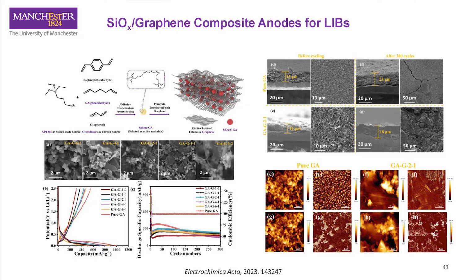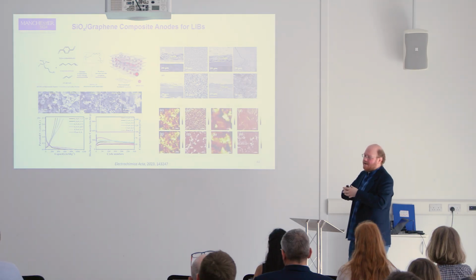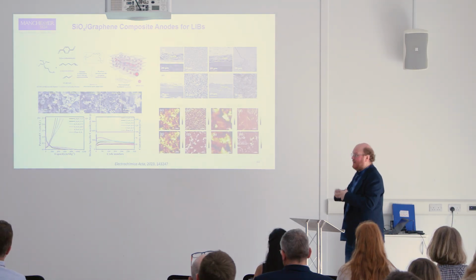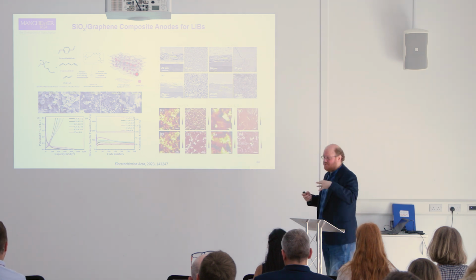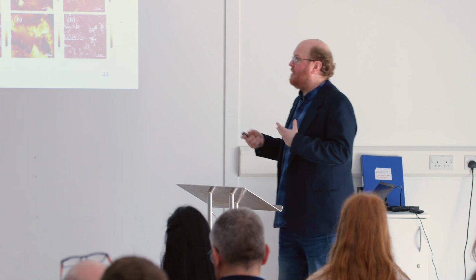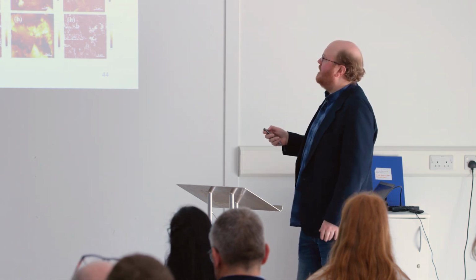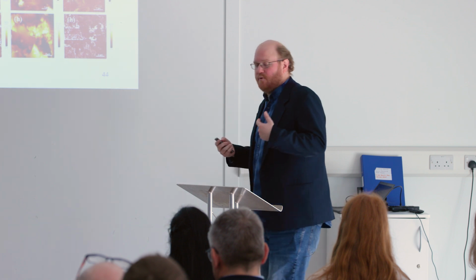So by actually interleaving graphene with silicon particles, the graphene can absorb that expansion without failing, without breaking, but provide that electrically conductive backbone. So by making these structures, composites of graphene and silicon or silicon dioxide together, you can get performance which is much higher. The capacity is much better than a single material, and the stability, it lasts much longer and is more stable than silicon would be by itself, or with carbon black, which is a traditional additive. So again, that's looking at how graphene as an additive can really improve the performance of some of these materials.